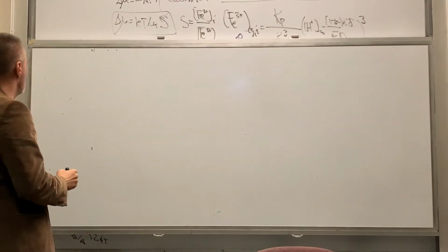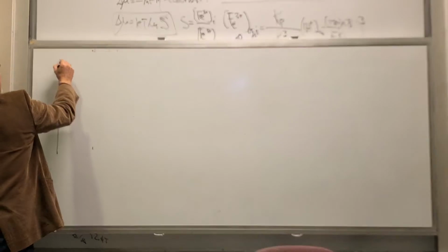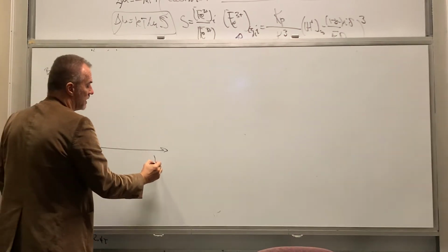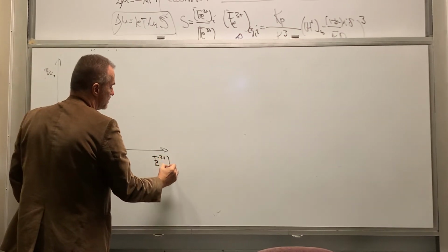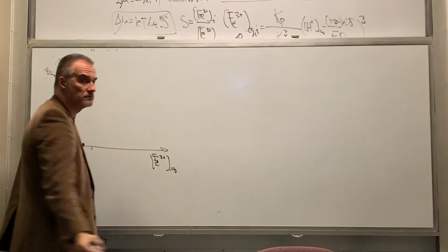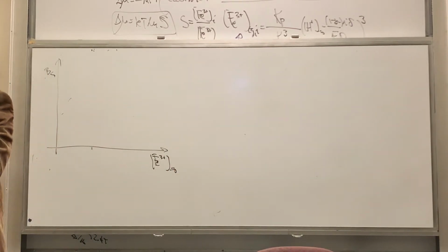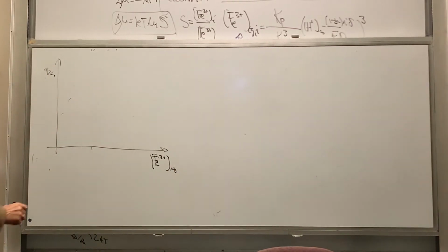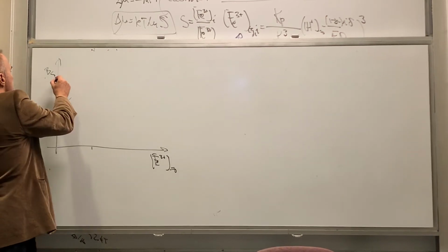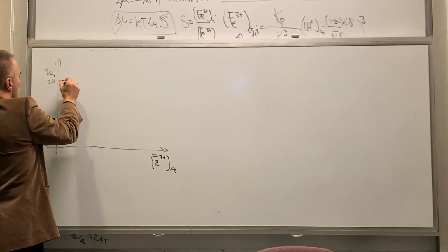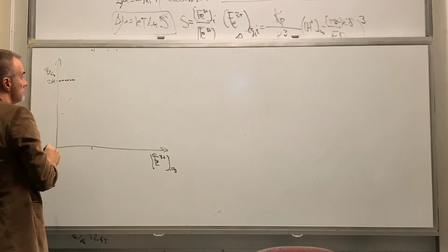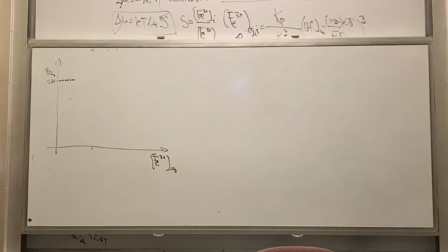So what do we do? We measure B sub S of our samples, and here each sample is produced with different iron 3+ concentration in the bulk. So we controllably add iron 3 in the bulk, right? So what happens? This is 2.4 Tesla, and so for very small concentrations, really nothing happens. It's 2.4 Tesla for every sample we measure.